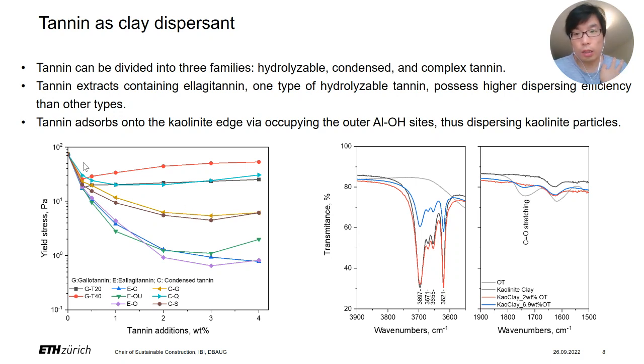After this test, we need to know why the tannin can be used as a dispersant, in other words, we need to understand how the tannin interacts with our clay particles. So we did some tests with XRD and infrared. We found that after incorporating oak tannin in the kaolinite paste, the intensity of these four hydroxyl group bonds are all decreasing, but not proportionally. The outer hydroxyl group decreased more than the inner one. So with the spectra, we can safely conclude tannin tends to interact with the outer hydroxyl of the kaolinite, which means tannin interacts or is absorbed on the edge of the kaolinite.